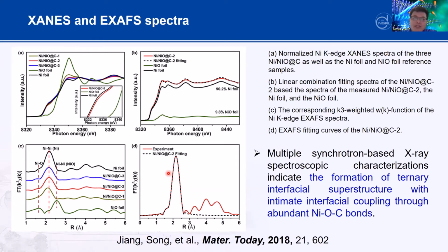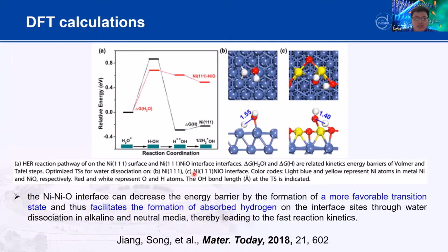How do we say this is ternary? Because carbon with the nickel oxide has an interface, and the nickel oxide with the nickel has an interface. Meanwhile, the carbon with the nickel metal also has an interface. So how does this interface work? We did the simulation, and we can clearly see the nickel-nickel oxide interface can really decrease the energy barrier of the formation, which is more favorable for the transition state and facilitates the formation of the adsorbed hydrogen.